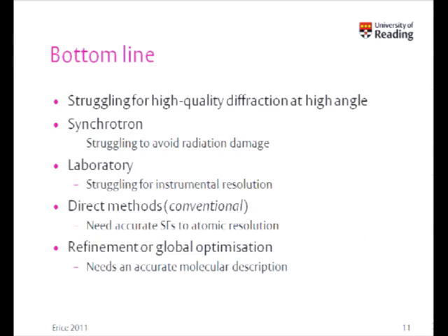So the higher the temperature, the quicker the drop-off will be. So what is the bottom line? Why am I telling you this? Well, it's simply to say that we really do, with molecular organics, struggle in many cases for high-quality diffraction data, particularly at high angles. Yes, we can go to the synchrotron, but as we showed this morning, you're sometimes struggling to avoid radiation damage. Normally you would think that with the extra photons you would get better signal to noise, and that's certainly true,